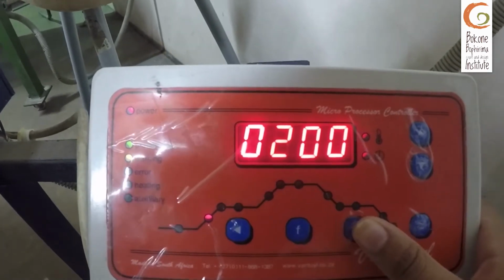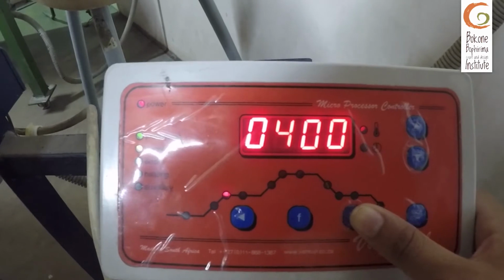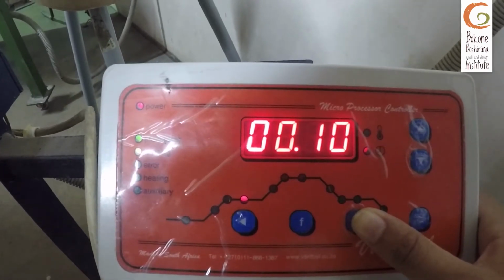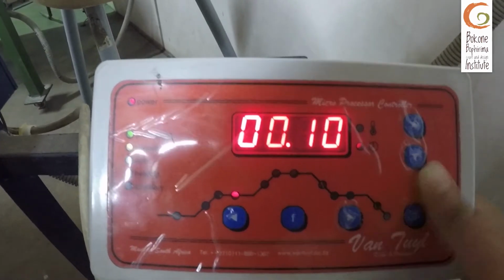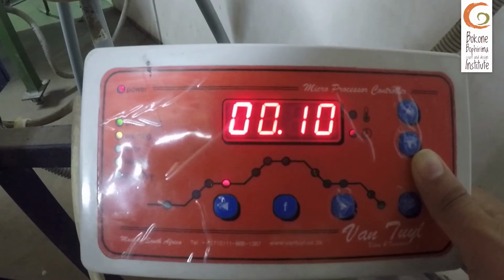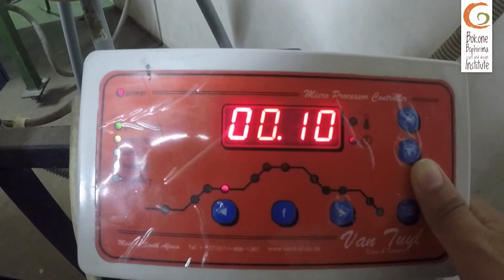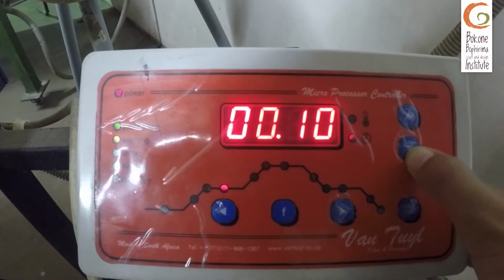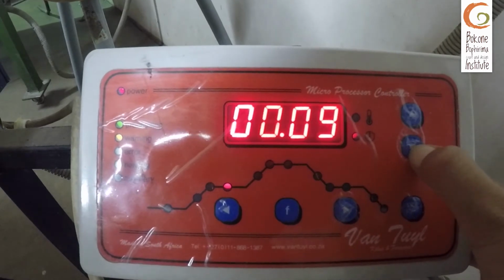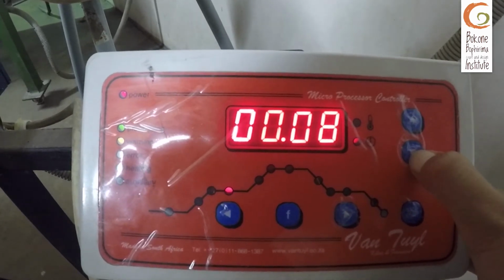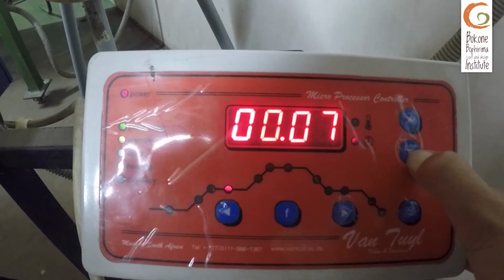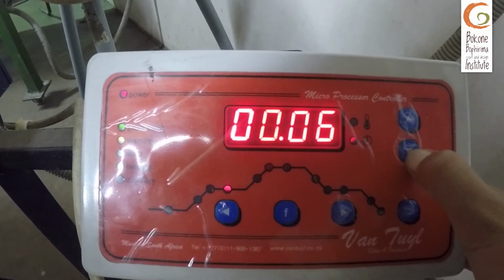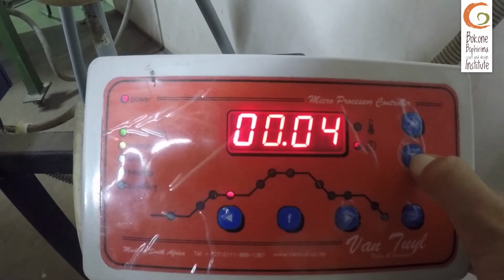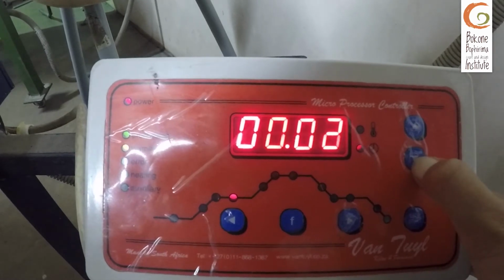And we are moving up our ramp at 200 degrees Celsius per hour to 400 degrees. And at 400 degrees, the glass is going to dwell or soak for 10 minutes. This is just to allow the contraction and expansion of the glass to get used to the temperature that it is going to.